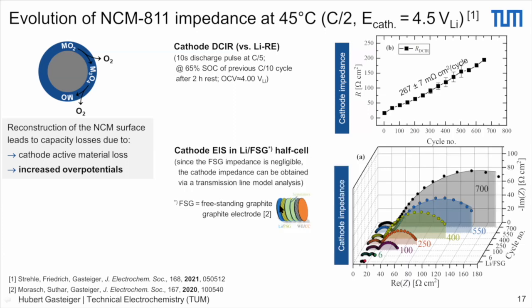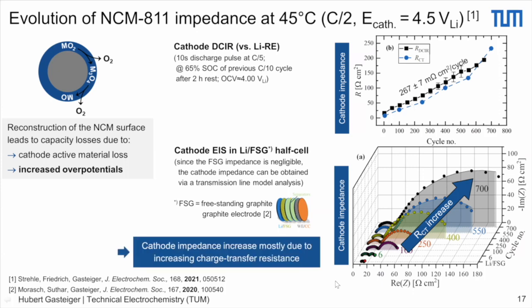If we do an experiment where we harvest the electrodes and we build them in a coin cell with a freestanding graphite electrode, so this is an electrode which has very, very low impedance, so this is shown actually here. So the total impedance contribution of the freestanding graphite would be half of what you see here, so negligible. Then we can analyze this as a contact resistance on the cathode active material, and then this is the charge transfer resistance. So that one also increases, and if we put it in the upper plot, what we can see is it more or less follows the DCIR resistance, which really is what you would expect. But what it shows is that the cathode impedance increase is mostly due to an increasing charge transfer resistance, which we believe is due to the formation of an oxygen depleted surface layer on the CAM.